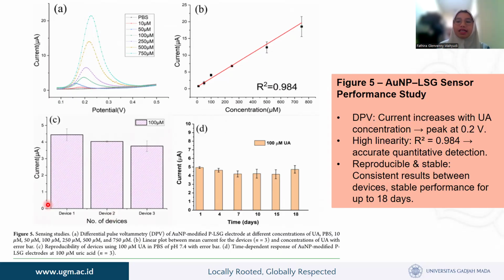And we see the reproducibility graph of three devices. Device 1 until 3 shows consistent current results for 100 micromolar UA, indicating stable sensor performance between devices. And with D, the time-dependent response graph shows that the current response remains stable up to day 18, indicating good sensor durability and storage stability. And the meaning of figure 5 is the AuNP LSG sensor is capable of detecting uric acid in a wide range, 10 until 750 micromolar, with high linearity. It demonstrates good reproducibility and long-term stability. This performance confirms the potential of non-invasive biosensors for real-time monitoring of uric acid levels.